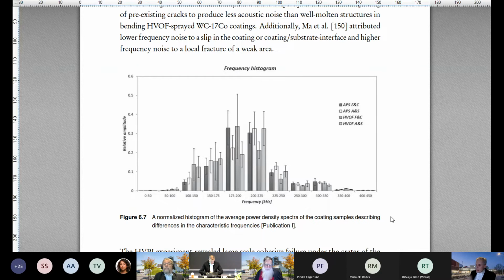So just to, if this is being presented to a manager where they just want to know a number, what is good and what is bad? If I look at the APS fused and crushed, or APS agglomerated and sintered, HVOF F&C, HVOF A and S, which one of those materials is good? In practice, you would want to have a low number on average all around, which would mean the least amount of cracking. It's just basing on this graph. But of course, it's a different thing if you have. And does your graph show that for something that we already know, like HVOF agglomerated and sintered might be the best coating?